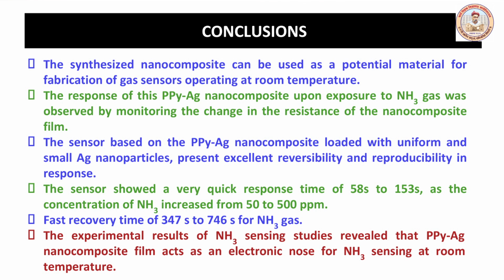Now let us go to the conclusion of the gas sensing we have studied. The synthesized nanocomposite can be used as a potential material for fabrication of gas sensor operating at room temperature. The response of this polypyrrole silver nanocomposite upon exposure to NH3 was observed by monitoring change in resistance of the nanocomposite film. Sensor based on polypyrrole silver nanocomposite loaded with uniform and small Ag nanoparticles presents excellent reversibility, reproducibility in response. The sensor showed very quick response time of 58 seconds to 153 seconds as concentration of NH3 increased from 50 to 500 ppm. Fast recovery time of 347 seconds to 746 seconds for NH3 gas is observed.